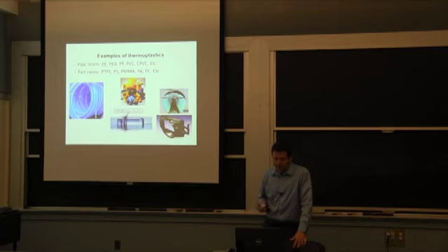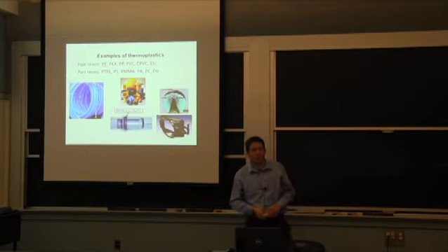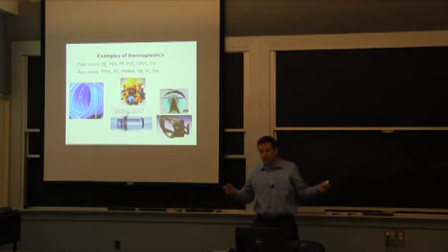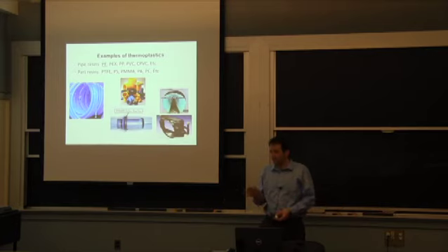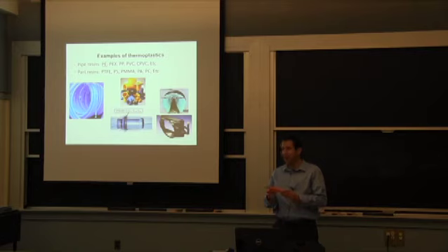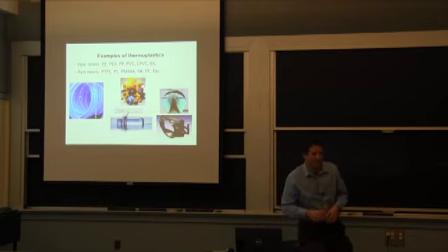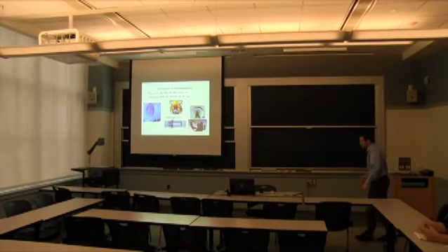So Professor Eager already mentioned it's used a lot for underground pipes because you don't have to worry about corrosion, both internally and externally, if you can maintain your stress level very low, and we're going to cover that today. I'm showing all sorts of pipes and fittings, and I have a pipe here that's for fire sprinkler. I brought this to the other fatigue and fracture class yesterday, and somebody thought it was for gardening sprinklers. It's intended to go up to about 200 psi, and it failed through slow cracking from the inside, and we're going to talk about that later.